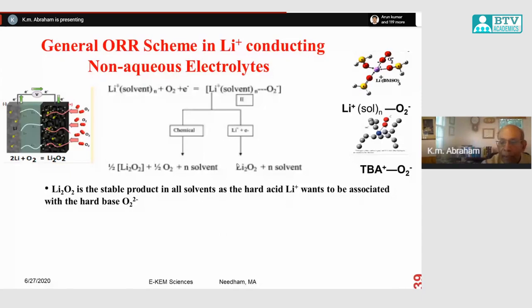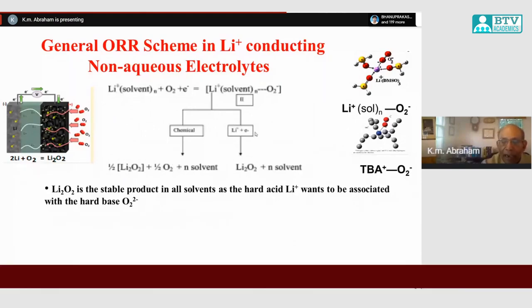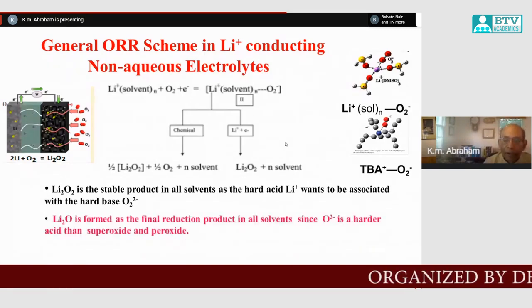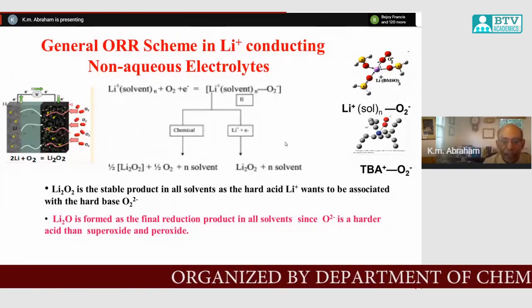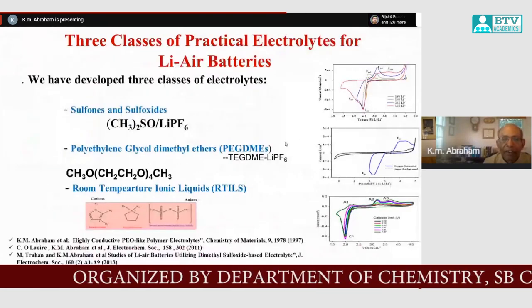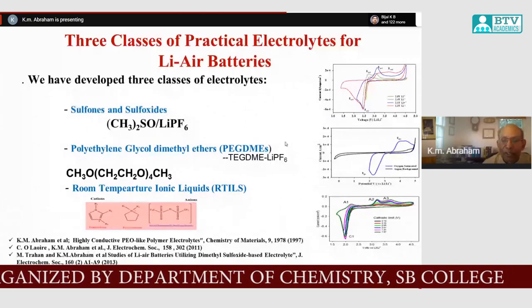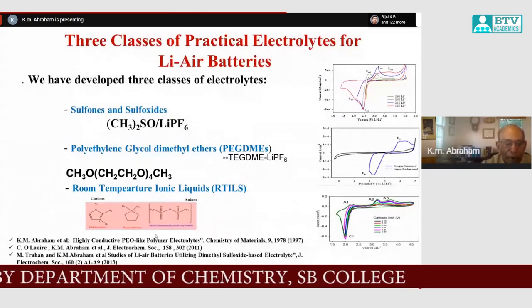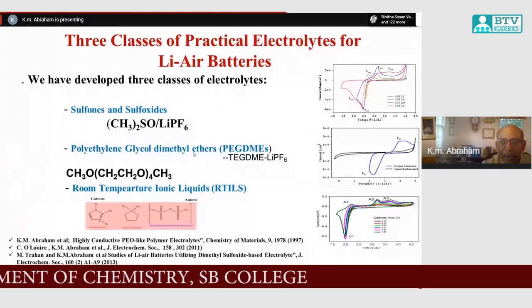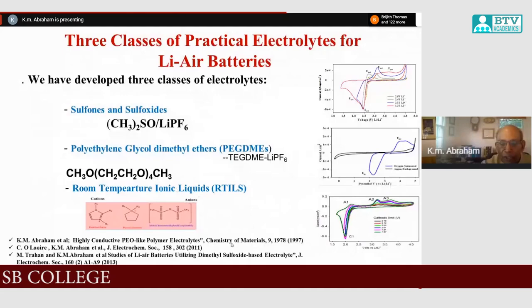And we developed this hard-soft acid-base concept to explain these things. With the lithium, finally you form lithium monoxide as the final product. And we developed several electrolytes: sulfones and sulfoxides, glycol dimethyl ethers, which are ethers, and then ionic liquids, another class of compounds.